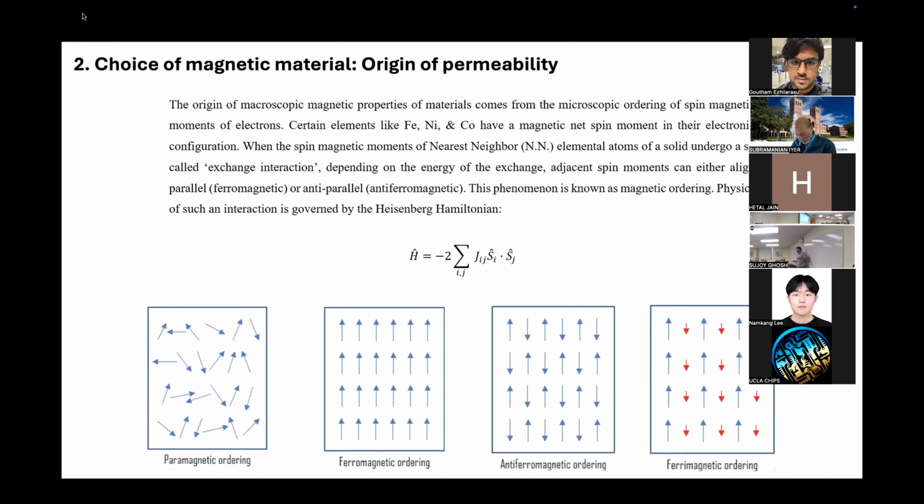For example, silicon is usually diamagnetic, right? Most materials are diamagnetic. They're not ferromagnetic. It's because when you consider the crystal structure as well as the outermost shell of the electron, the exchange interaction integral is very small, so they don't couple as much. Ferromagnets are highly coupled materials, where the spins next to each other are highly coupled with each other. That's what gives you ferromagnetism, and that's really a fundamental property of the chemistry of the elements that make up that crystal.